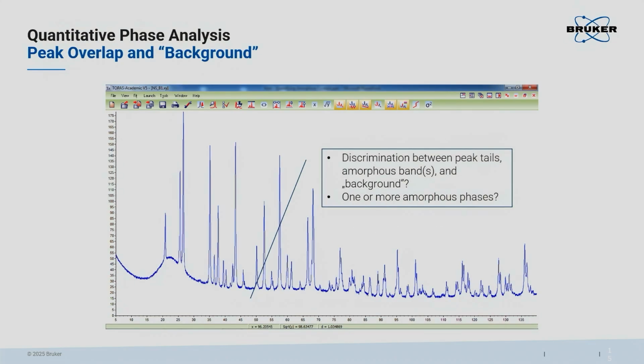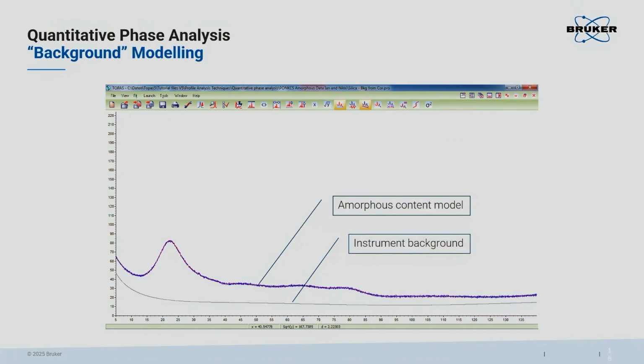So here in this particular case, I had the luxury of a pure amorphous sample, because this here is a mixture, an artificial mixture with known weights. If I know the amorphous content intensity distribution, then I can use it as a refinement model. I can determine this intensity distribution, for example, with a series of single peaks, or maybe with a Le Bail refinement. I show this later. Fix the intensities and scale them up and down in the refinement. So as a model for my amorphous content.